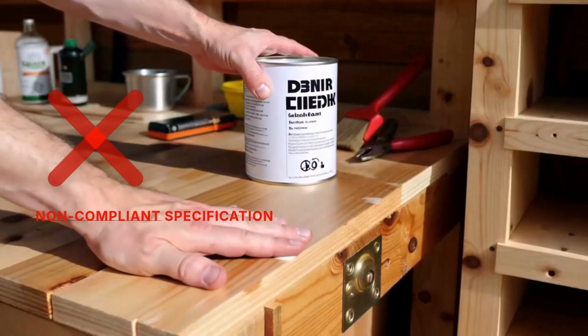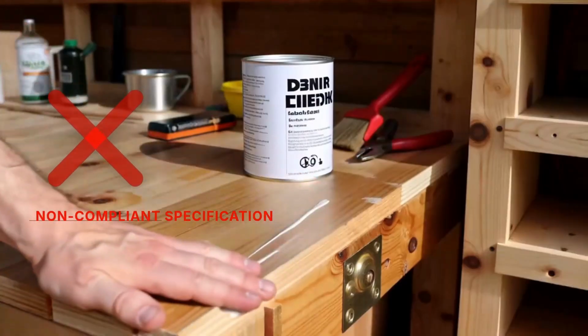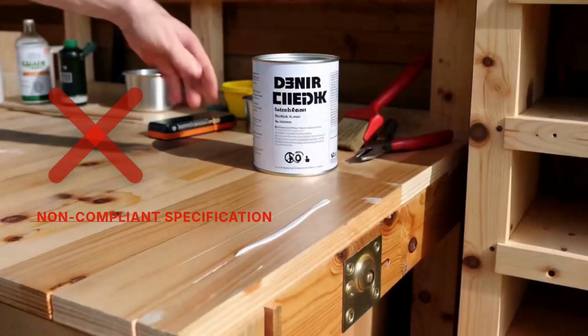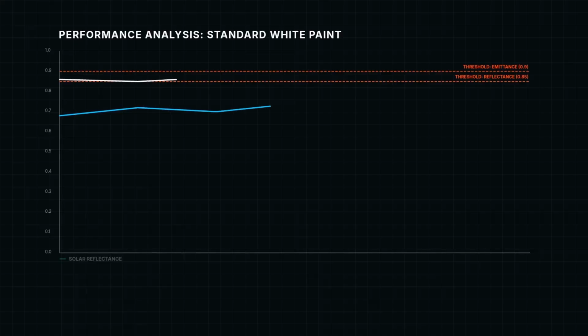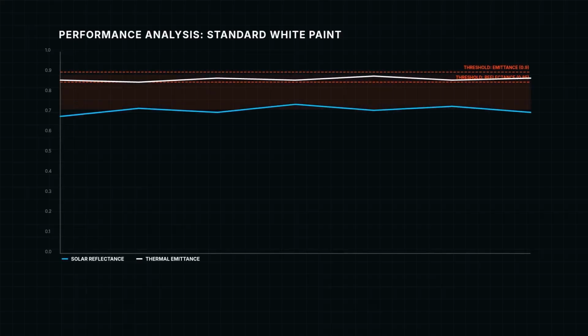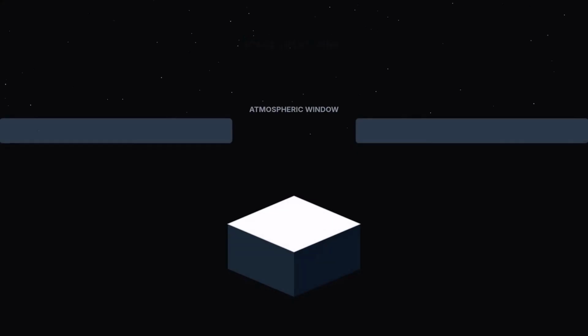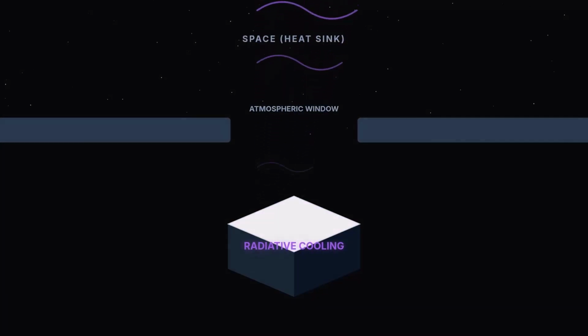Do not substitute standard white exterior latex paint. Most exterior latex products achieve solar reflectance between 0.65 and 0.75 and thermal emittance between 0.85 and 0.88. These numbers perform adequately, but fall below the threshold required for documented sub-ambient cooling. You need both numbers above their respective thresholds simultaneously to access the full atmospheric window effect.